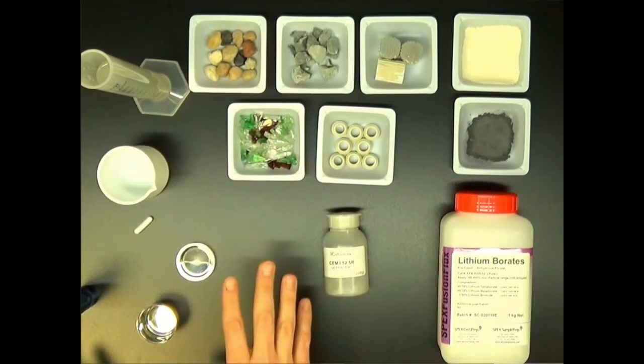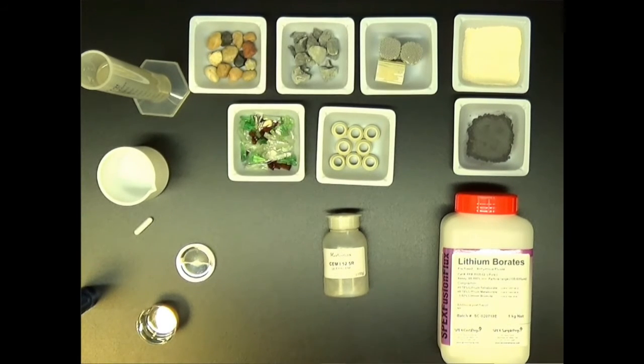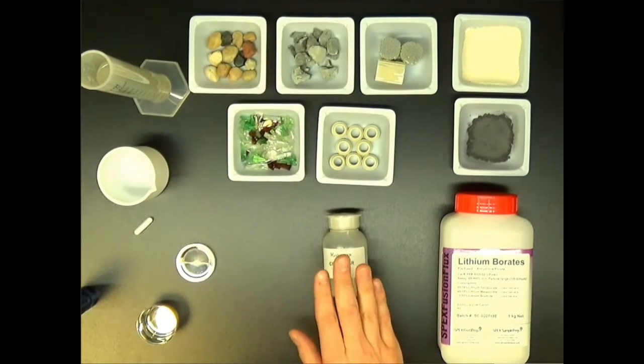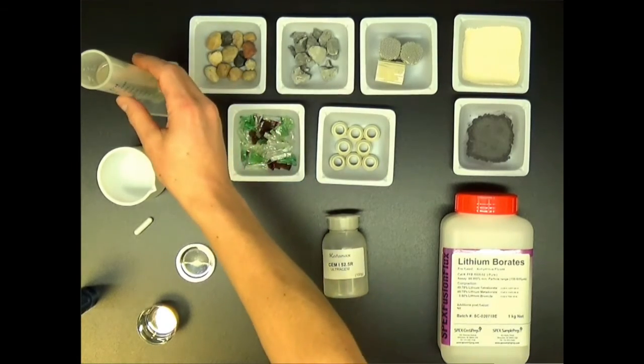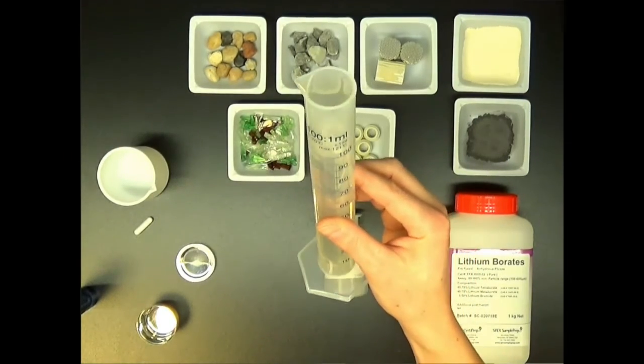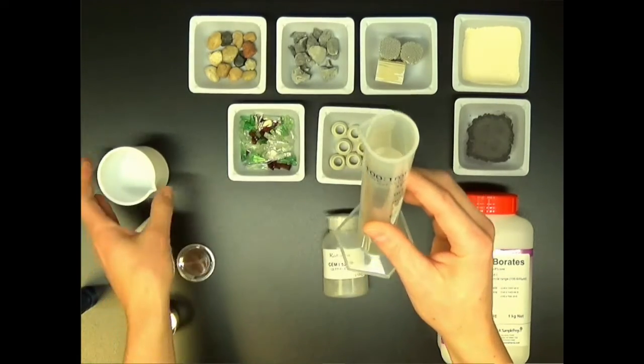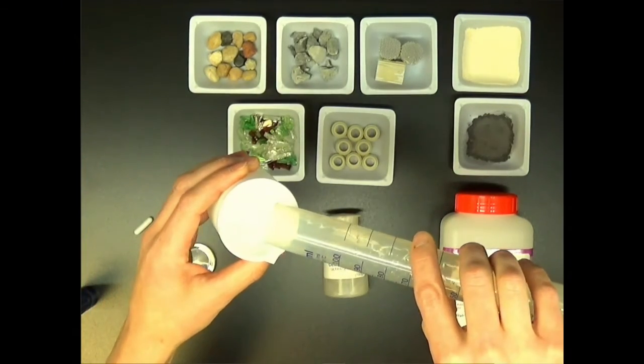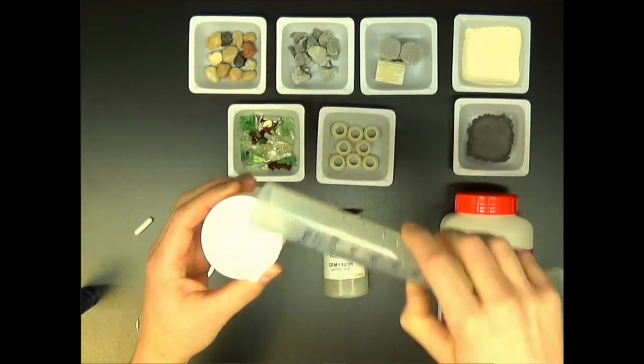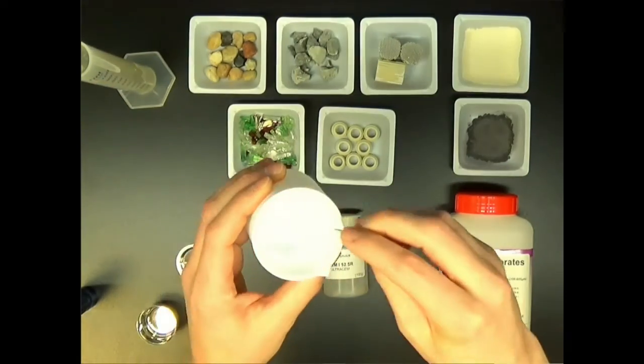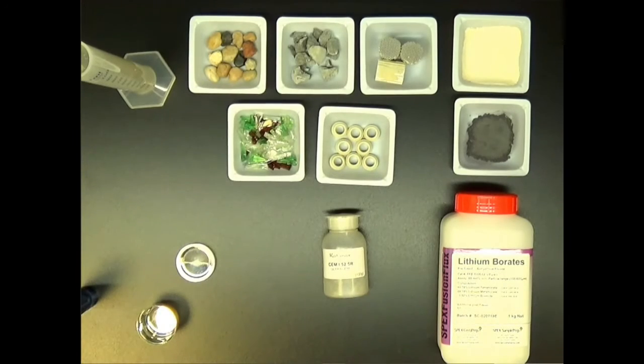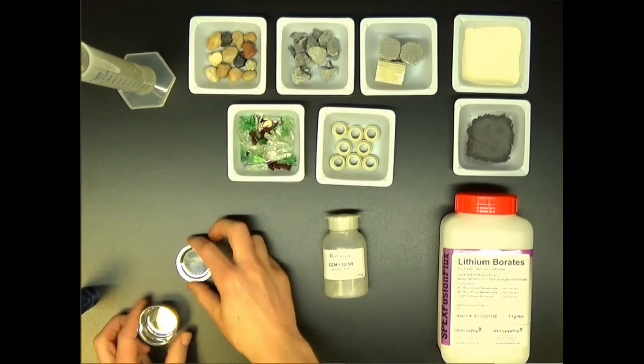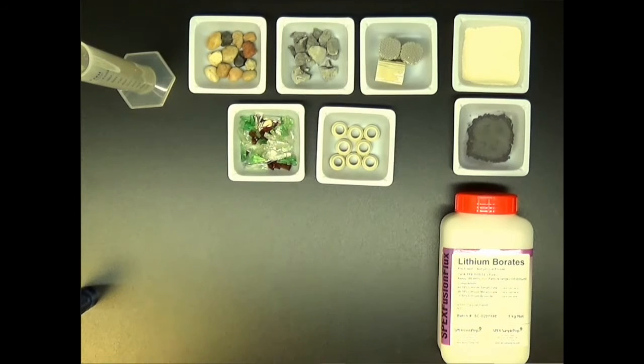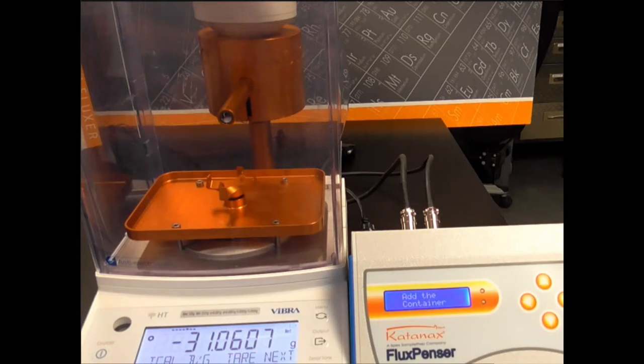We will prepare fusion beads, and we will also prepare a solution for ICP analysis with the same sample. So I will prepare right now 100 milliliters of dilute nitric acid that I will transfer into my Teflon beaker, add my magnetic stirrer and put it on the side for later operation. So I will take my platinum crucible, my sample, and I will transfer it right away to my friends in the laboratory that will help me to automatically weigh the flux.